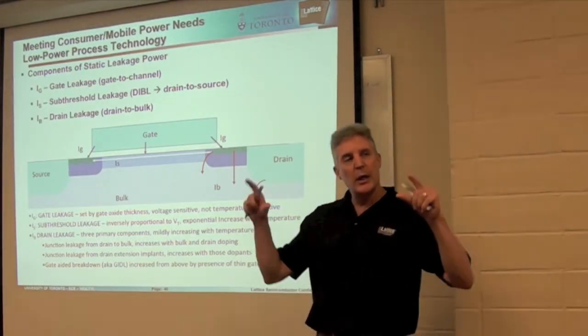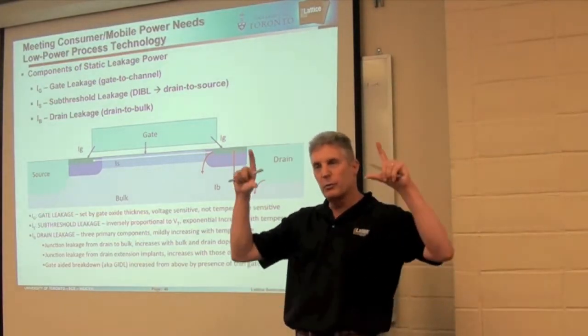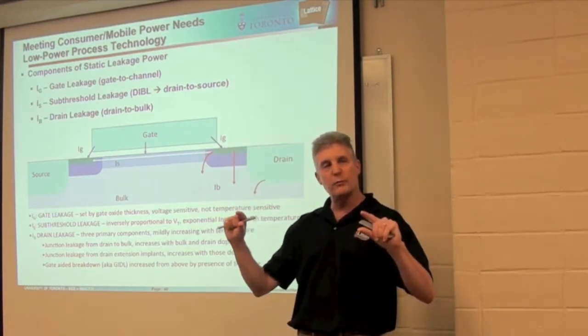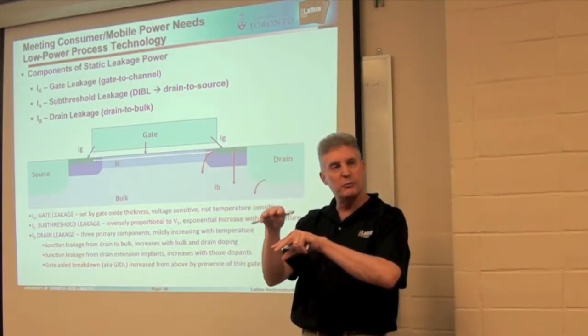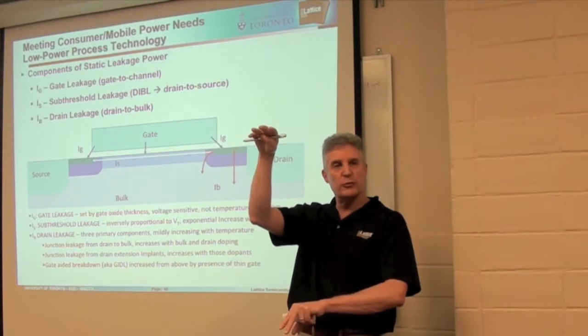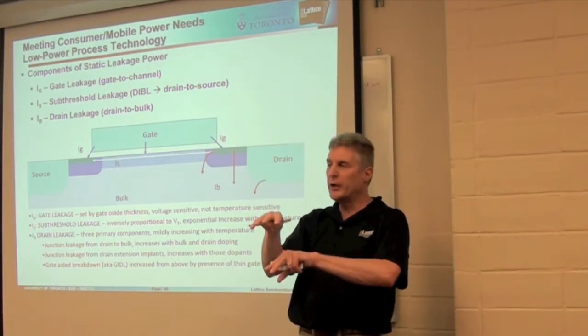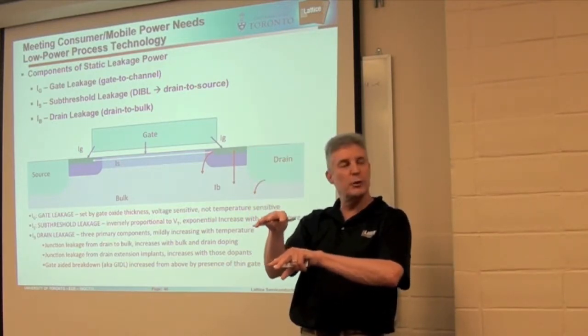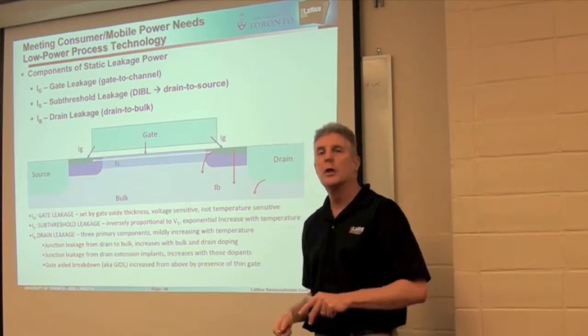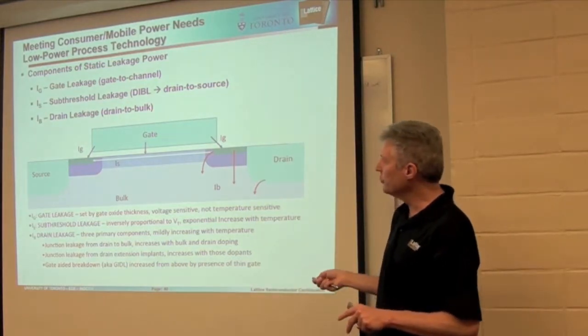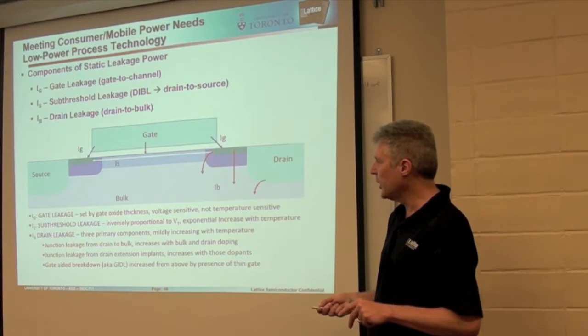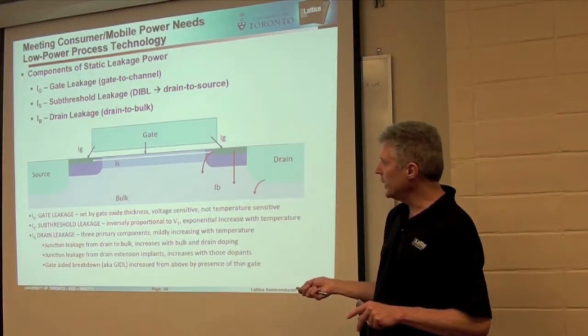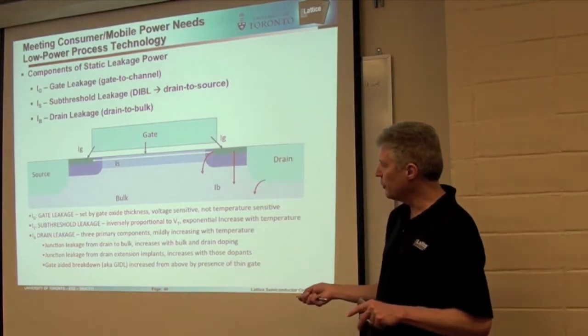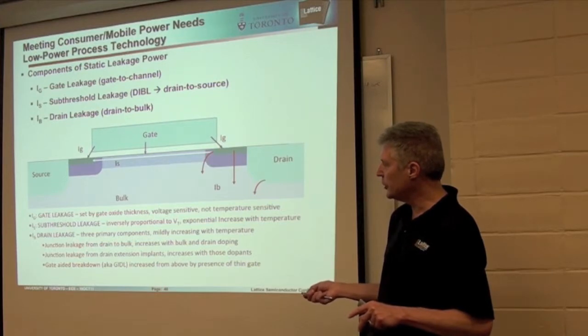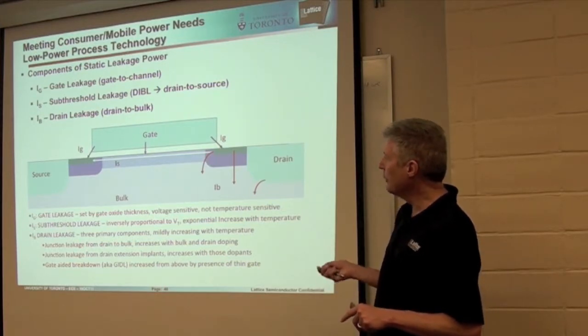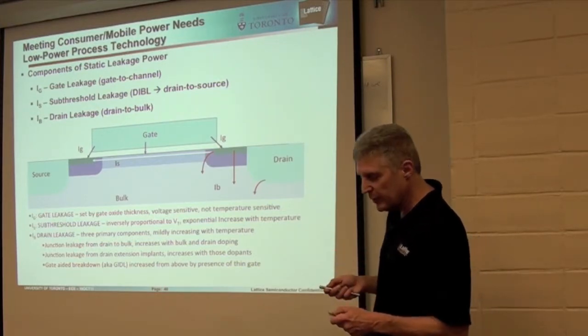And importantly, as you scale your supply voltages from 3 volts to 2 volts to 1 volt, you need to scale your threshold voltages. So we used to have threshold voltages of 1 volt on transistors. Today we're operating with threshold voltages of 200 millivolts and going lower. So that's part of the reason subthreshold leakage is becoming dominant. And finally, the drain leakage is a combination of a number of subtle features, junction leakage and gate-induced drain breakdown. I won't go into those too much, but those are the three leakage components.